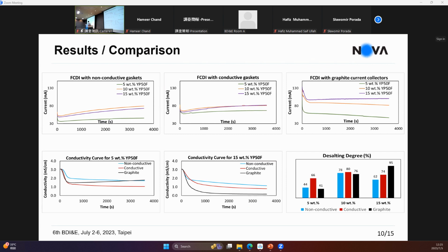For the 5% and also for the 10% weight percent of the carbon in the flow electrode, actually the conductive gaskets even performed better than the graphite current collectors. And we think that it's because when we printed the 3D gaskets, they are never completely flat. There are some rugosities on the surface of a 3D printed gasket, and we believe that this can create some mixing of the flow electrodes.